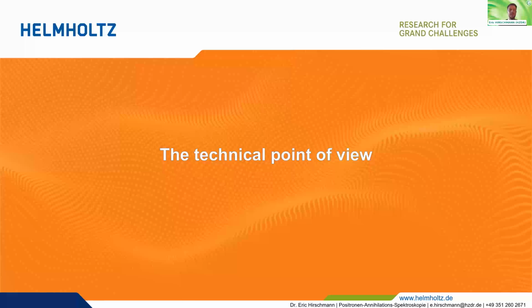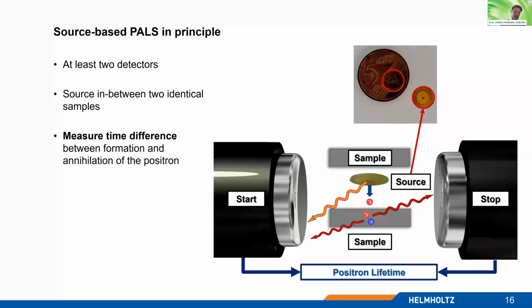This leads to the technical point of view. Now, what can we do, or how is it done at the HZDR? First of all, we start with the more simplistic kind of method, which is the source-based PALS. So in principle, you need a source, which is here in the upper picture, the orange foil, and in the middle of this orange foil, there's a sodium-22 source, which emits the positron into your material with a high energy. So this is for bulk studies.